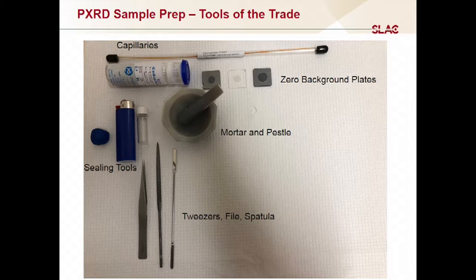You pack this down into a bed of powder, and typically it's good to do this on one of these zero background plates. These are either silicon, which are the ones on the ends, or quartz, single crystals which have been cut at a very specific orientation so that during a measurement of a powder, you never illuminate any of the Bragg peaks. Or if you do, the Bragg peaks go in some other direction that you're not looking in. Because they're very high quality crystals, they have basically no diffuse scattering. All of the scattering goes into the Bragg peaks. And as long as you don't look where the Bragg peaks are, you basically get zero background. So these are very handy.